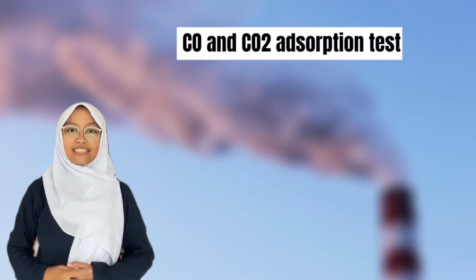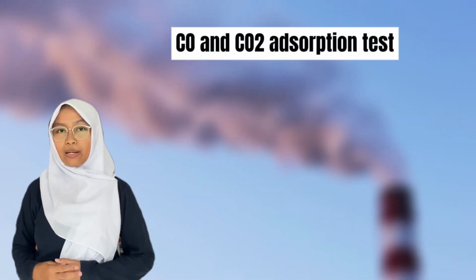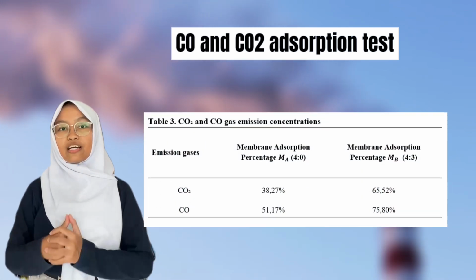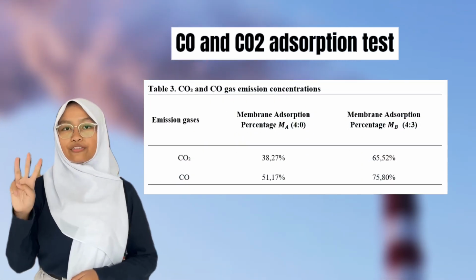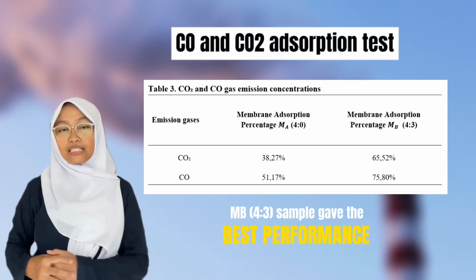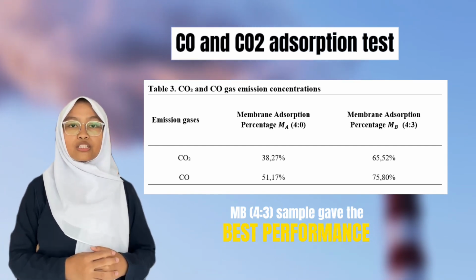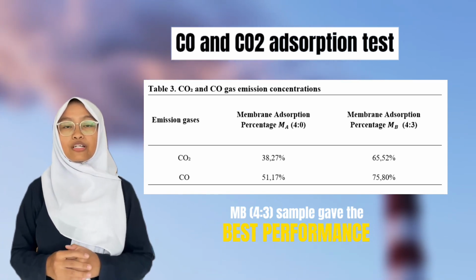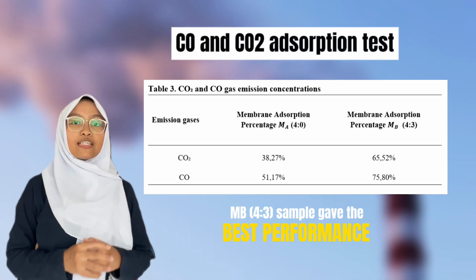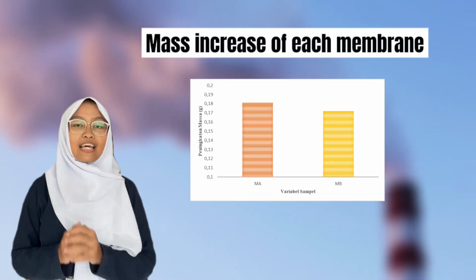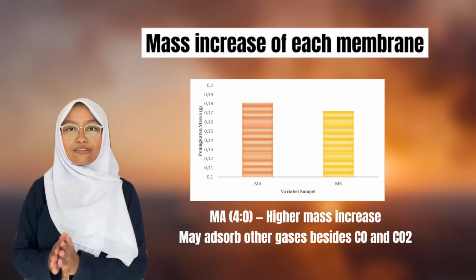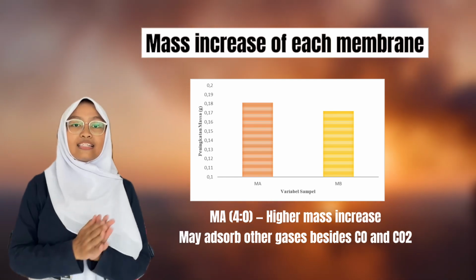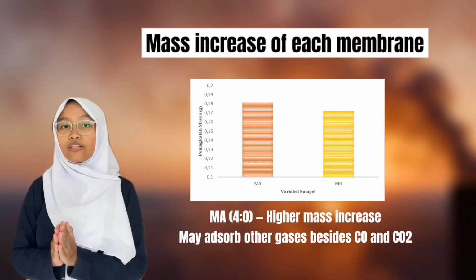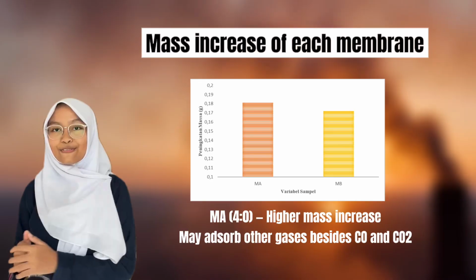The researcher also tested the absorption ability of MMM with cellulose acetate and non-activated carbon ratio of 4:0 and 4:3. The MB sample showed the best performance, with a CO2 absorption percentage of 65.52% and CO of 75.80%. Although the MA sample was not better in CO2 and CO absorption, the MA sample showed a higher mass increase, indicating that the MA sample might also absorb other gases besides CO2 and CO.